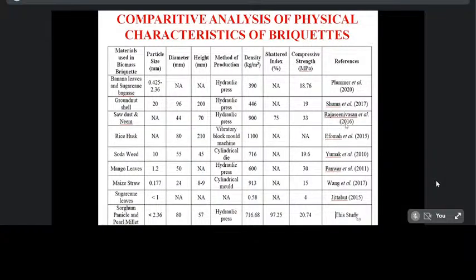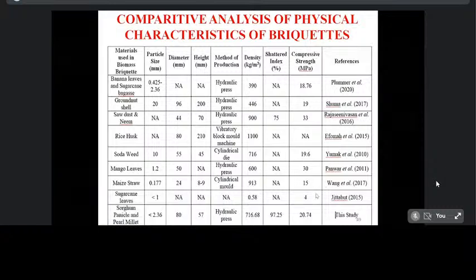So most of the studies do not follow the Shatter index value. They took sawdust and neem as per Rajesh Srinivasan et al. 2016, and their Shatter index value is 75%. But here our sorghum panicle and pearl millet briquette has 97.25%. Okay, so the compression strength also varied from 4 megapascal to 20.74 megapascal.